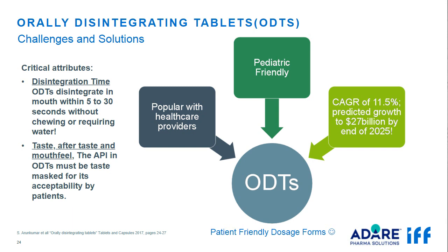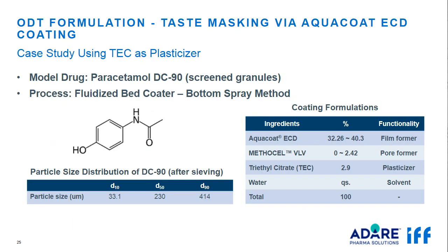In this case study, paracetamol was selected as a model drug and coated with Aquacoat ECD in a fluid bed using the bottom spray method. Methocel VLV, which is a very low viscosity grade of HPMC, was used as pore-former, and TEC as plasticizer, as shown in this table.